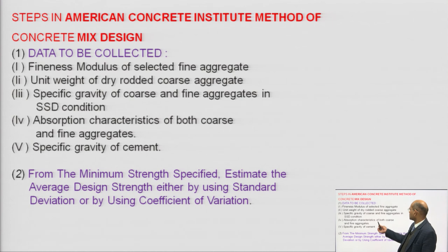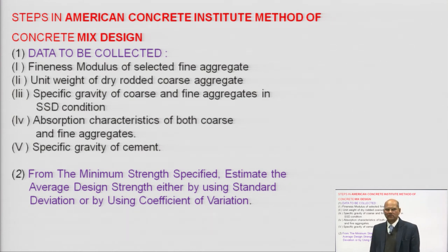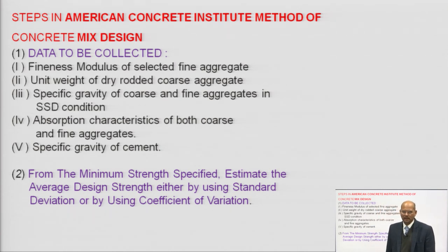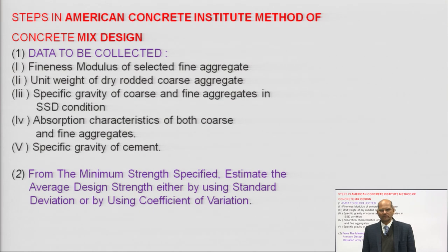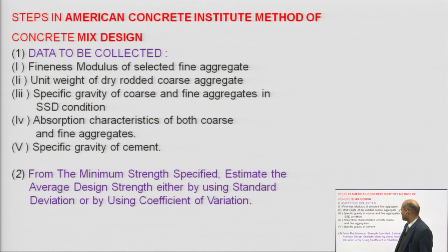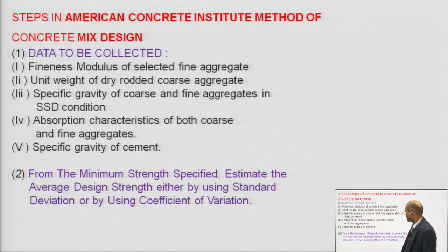We also need the specific gravity of coarse and fine aggregate in saturated surface dry (SSD) condition, and the absorption characteristics of both coarse and fine aggregate — how much percentage of water they absorb in dry condition and how much moisture is present when obtained from the field. Additionally, we need the specific gravity of cement.